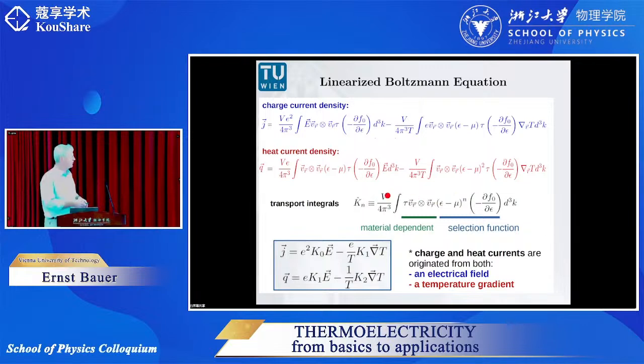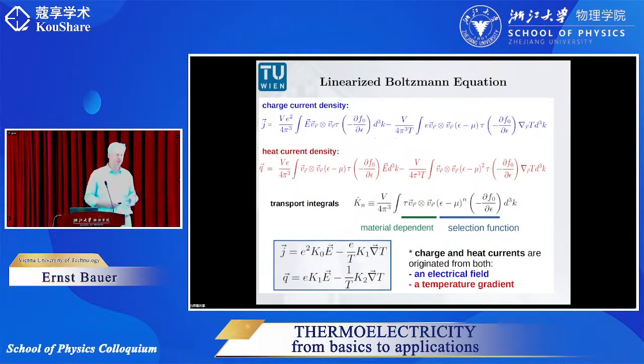Then making a little bit cosmetic, as you can see here, some of the parameters are summarized in so-called transport quantities. One can see that the charge current and the heat current density can be expressed in a quite simple form. And if you use these simple forms here, you can even think about how to simply measure these quantities. You know, in case of an electrical resistivity, we do not have a temperature gradient along the sample. So this second term goes away.